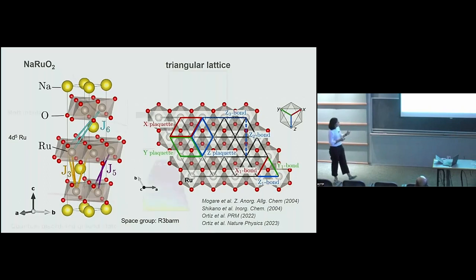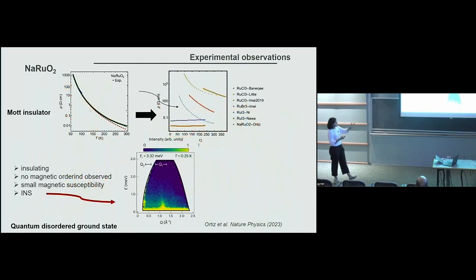So what we did is, and in fact this is the result of the experiments that Stephen was showing: the system is insulating, there is no magnetic ordering observed down to very low temperatures, and this is the type of inelastic neutron scattering experiment. Stephen was talking about the quantum disordered ground states. The question is, where does this come from? There was also the discussion of possible impurities, but otherwise, what are the exchange interactions in this system?